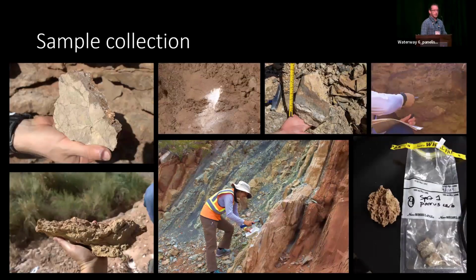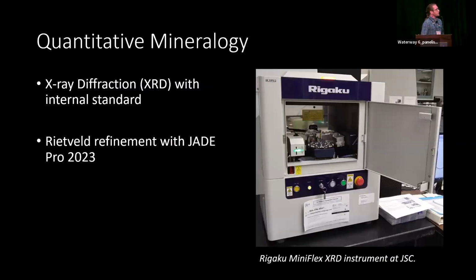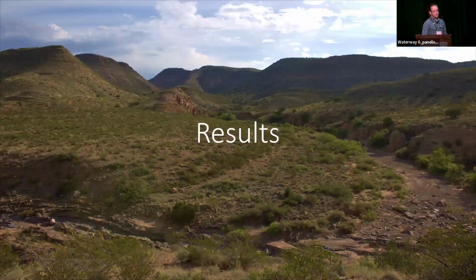So we collected samples from these two sites. Mostly we just went with hand samples, sometimes with our actual hands. Brought them back to Johnson Space Center for analysis. And we mainly did quantitative X-ray diffraction. We used an internal standard of 20 weight percent corundum so we could get quantitative mineralogy using Rietveld refinement with the Jade Pro software. All right, we did all this.